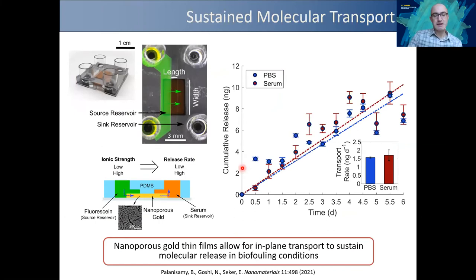So one big problem, obviously, with drug delivery is that eventually you run out of drug molecules. So I had a really talented undergrad in my group, and we just published this paper where we used the basic idea of an oil lamp wick analogy, where you have a reservoir and the molecules are transported laterally in plane through the film and released from the other side. And this actually works remarkably well. You can even sustain release in serum, where the biofouling does not deter the release rate. I'm going to talk a little bit more about the mechanisms for this. But with this technique, you can imagine that you can have multiple electrode arrays where in the peripheral electrode pads, you can actually put drug molecule reservoirs and route them into the culture through the traces. And I'm really excited about coupling this with some other techniques that we are looking into at the moment.